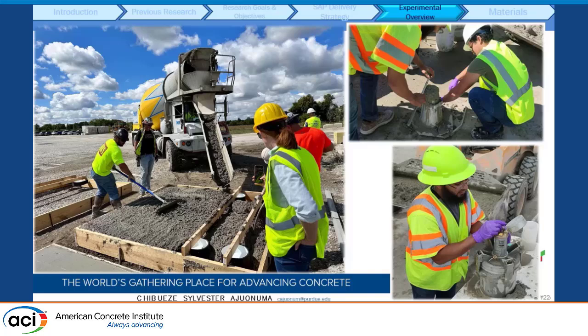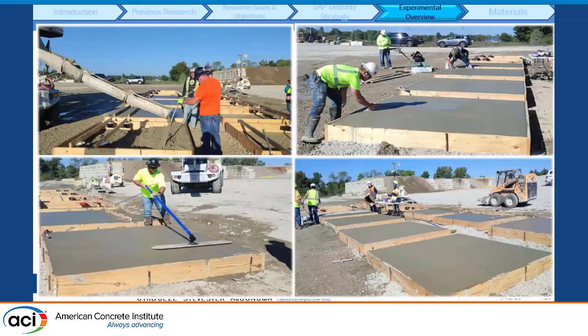We also made provisions and improvised for some cylinders, which we eventually extracted to test for scaling resistance. And we tested fresh properties, both the slump and the air content, in the field. This is the work of the professional concrete finishers. We ensured that the concrete surfaces were finished to replicate a real-life application.